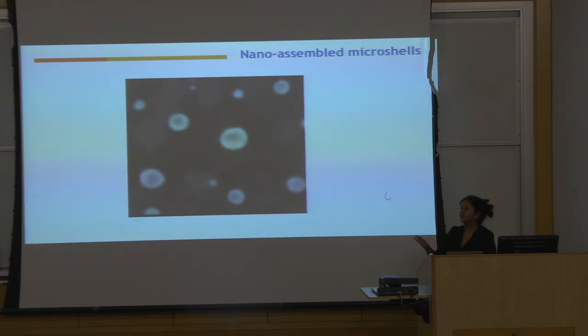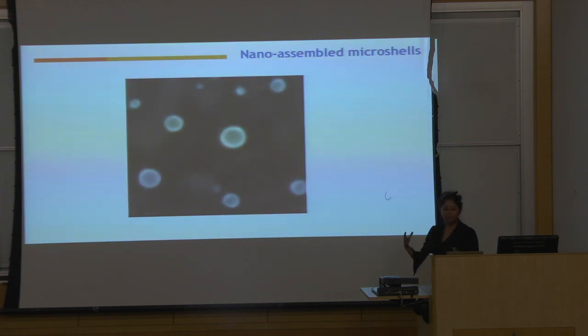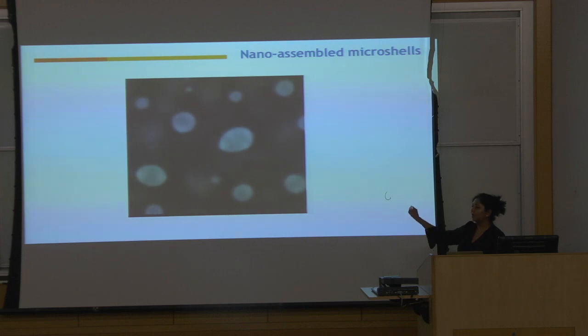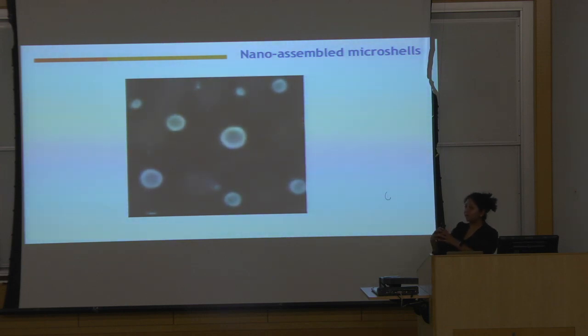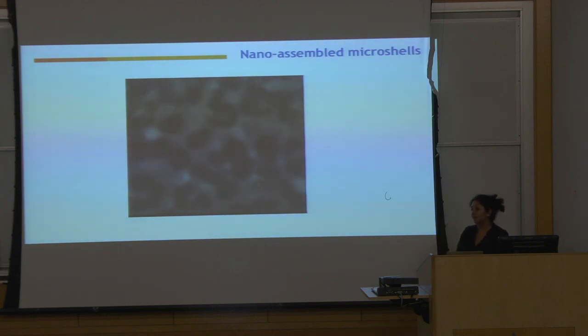Of course, it would be a function of nanoparticle density as well. You have to have nanoparticles there. So what we think is happening is as you cool slower, it gives the liquid crystal more time for the nanoparticles to come close together into bigger aggregates. So even the shells themselves are not the equilibrium. We are sort of freezing the system here to form the shell. If we cooled it more slowly, a couple of shells would have come together eventually to form a bigger shell. So that's what's determining the size. We can put this system in liquid nitrogen and take it out, and we get very, very small shells that we can barely see in a microscope.